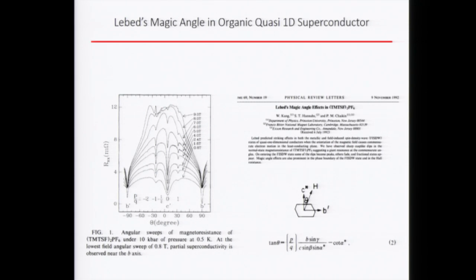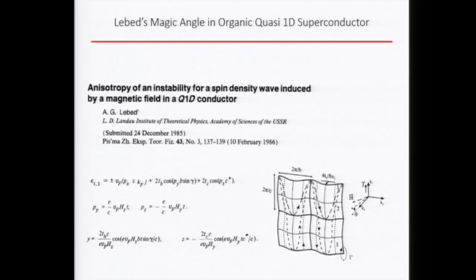There are various ways to understand or explain this, and one of the popular ways is to realize that in this quasi-organic 1D system, you form Fermi surface sheets. When you apply a magnetic field in this geometry, if you have a closed Fermi surface, electrons circle around a closed orbit. But if you have a Fermi surface sheet, then the electron will try to traverse a path on the Fermi surface sheet that is perpendicular to the magnetic field and on a constant energy contour. So if you apply it at a random angle, this path will never return to itself.